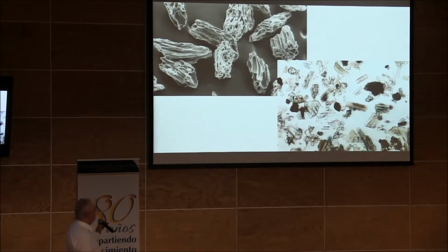On the lower right, you see an optical picture of the system. It looks a little more complicated because the optical properties between crystals and glass are very different, and they're very easy to distinguish. That's why we use optical analysis of rocks. And you can see that there is a clear white phase, which looks like broken pieces of glass. It literally looks as though you took a water glass, crushed it up, put it under a microscope, and you would observe a very similar thing. So the glassy phase, the white colored phase here, is dominating. There are other phases. There are crystal fragments which are here, including the black parts that you see. But the matrix, the host of the whole system, is a glassy phase.